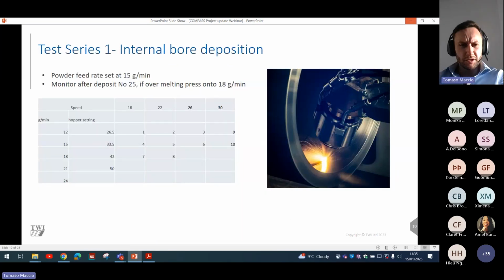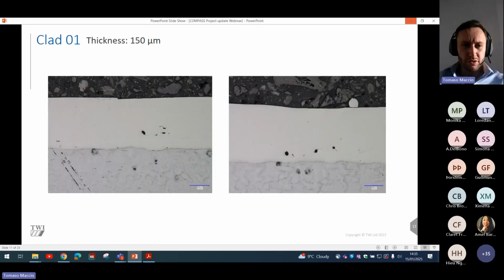So these were the initial test series that we completed within the project, and some initial results. You can witness within this slide, there's quite a few defects within the deposit. So the substrate has a small amount of defects, but these defects are not desirable at all. Fairly large, so we're talking around 10 micron defects here. This is not something we want when we're exposing a clad to a corrosion-heavy environment. So these parameters were refined further on the large-scale machine, and I'll share those later on in the presentation.